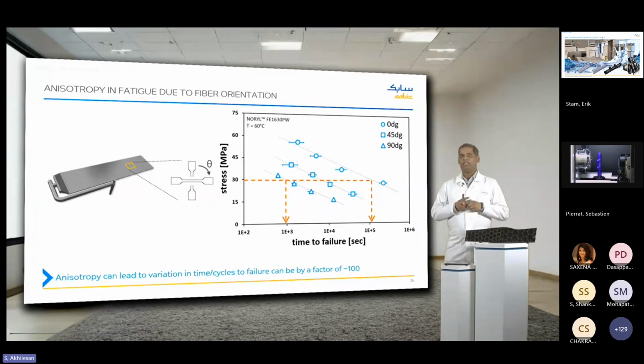For example, let's take 30 MPa as marked in the graph here. At 30 MPa, the cycles to failure at 90-degree orientation is about 1,000, while that at the 0-degree orientation is about 100,000. So for this particular material that you see on the graph here, the variation is about a factor of 100 when orientation is accounted for. Hence, considering anisotropy in the fatigue models is very, very important.